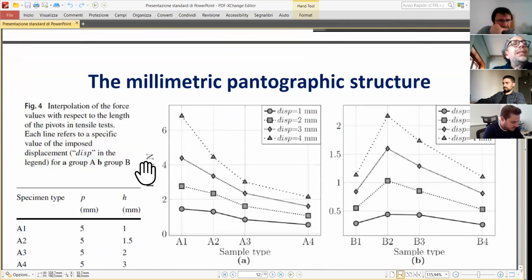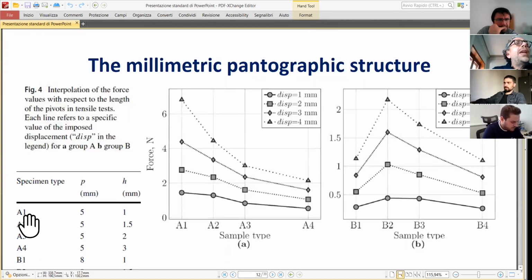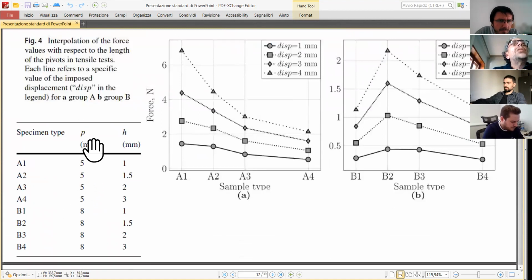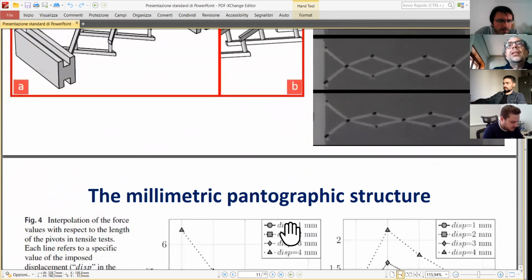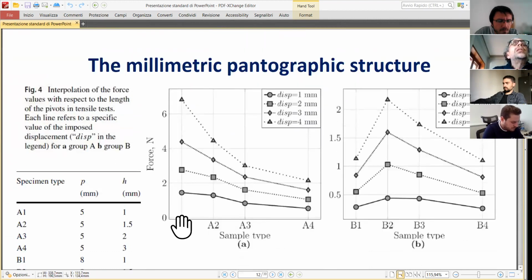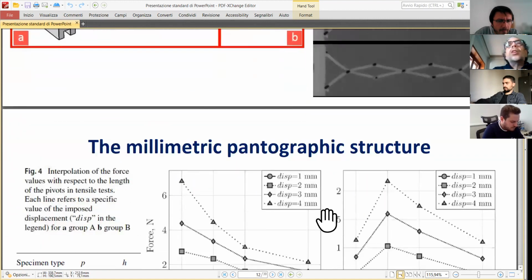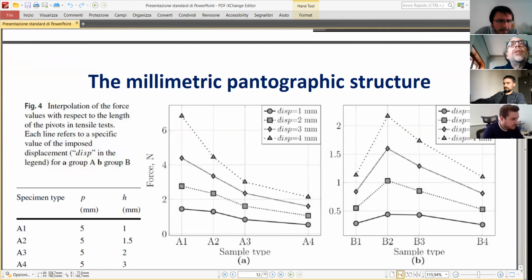This is also proven experimentally with pivots of different types. You know, we have A1, A2, A3, A4, B1, B2. They are pivots. Here are the dimensions of the pivot in the millimetric structure, this one, okay? When you impose this displacement here and you plot the force as a function of the displacement, what do you get? For displacement 1 millimeter, you get this force. 2 millimeters, you get that force, and so on. So you have the dependence displacement-force, okay, and what you see with B2